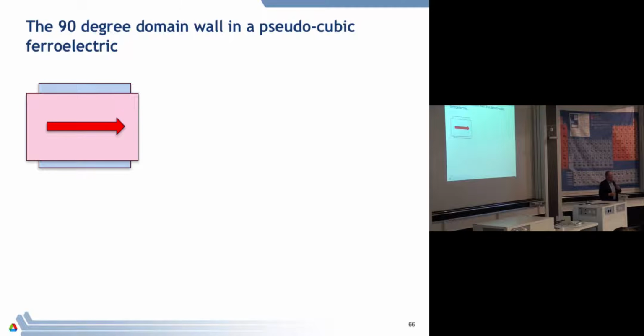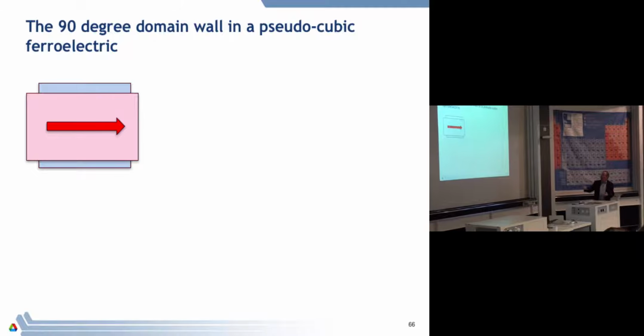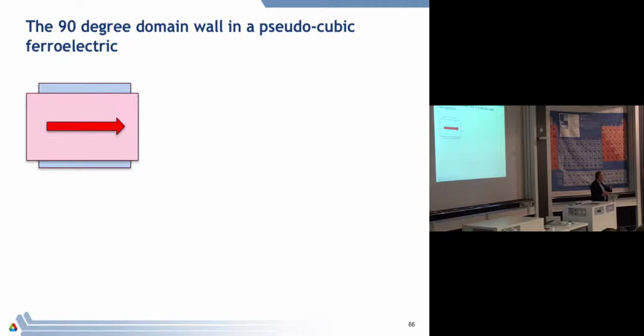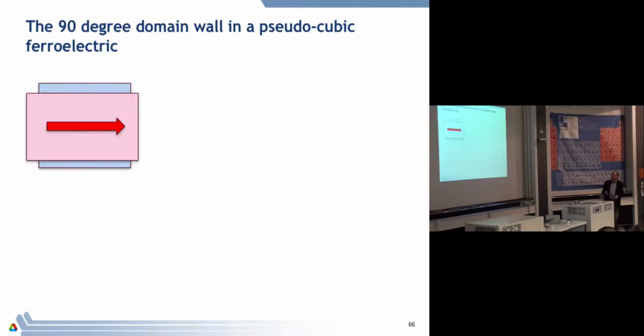it will establish a spontaneous dipole moment, a polarization moving in here. And what that means is that every titanium atom in every unit cell moves in the same direction by a little bit, and that generates a set of dipoles, and they all add up, and that produces a macroscopic polarization. Okay? But when I do that, the crystal will also change shape, because there's a direction associated with it. Everything moves there. So macroscopically, actually, the crystal will change shape, and you can see this.